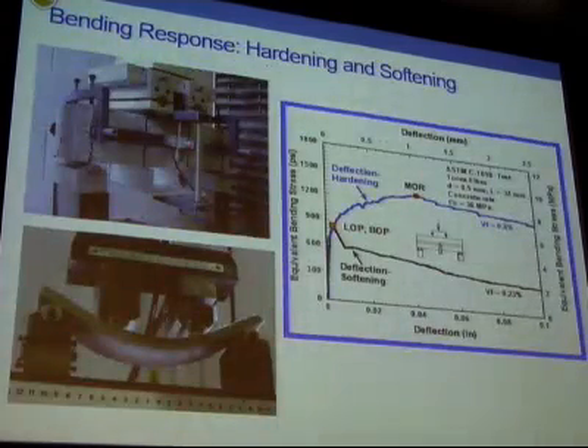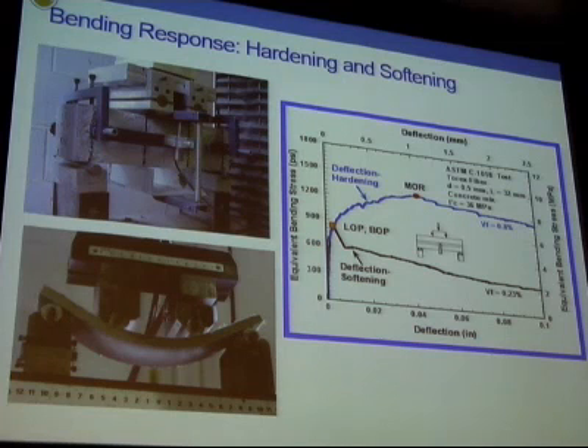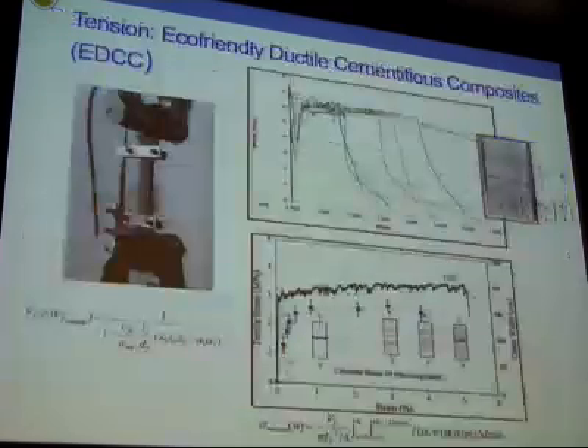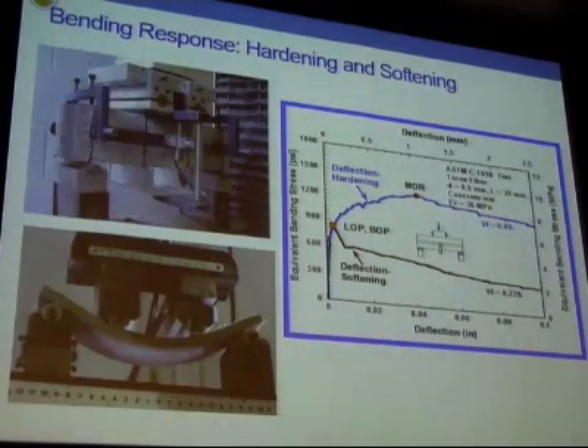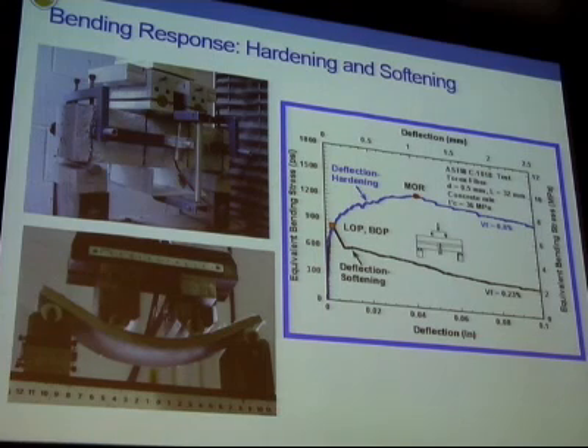So now if you look at all of the work that has gone into generating fiber-reinforced concrete or optimizing these materials, 30 years ago we would have had a response which is what we call a softening response, or a deflection softening response. But by understanding the mechanisms of these materials, what we can now get is what we call a strain hardening response. So you can get a material which almost behaves like steel. And you can actually create materials which now can bend. This is actually concrete, which can bend and carry more strain than up to 5 or 6%.